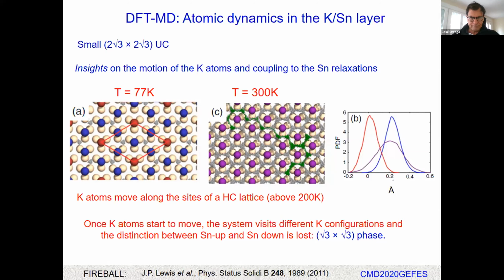Essentially, the main result that we get from these molecular dynamics simulations at different temperatures is that the potassium atoms start to diffuse along the surface above around 200 Kelvin, and they do it by jumping between different sites of a honeycomb lattice. In fact, these sites are the T4 sites for the silicon 111 surface, excepting those T4 sites that are already occupied by the tin atoms. So they move jumping through the sites of a honeycomb lattice. And once potassiums move on the surface, the distinction between tin up and tin down is lost, and all the tin atoms are equivalent in a time average.